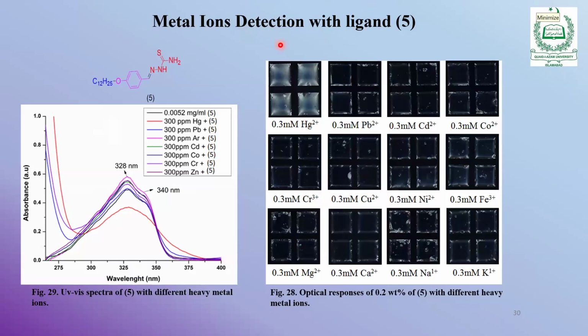Now we are adding the metal ions. So metal ion detection with ligand 5, as we have seen that this sensor was specially designed for the mercury ion detection. So we added the highest concentration of mercury in the liquid crystal sensor. So 0.3 millimolar is very high concentration of the mercury. Not only mercury, we also added the other metal ions to check whether it is selective only for mercury or it can interact with the other metal ions also. So these different 12 tests were done with different metal ions, same concentration.